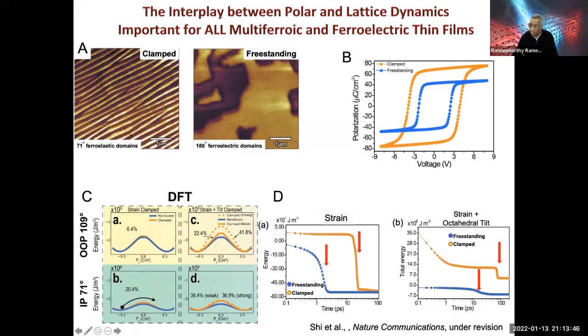Now, we went back to our theory colleagues, both DFT and phase field, and I'll just show you the DFT data. What Jorge again showed was that if you look at BFO, it switches in two steps, 109 degrees out of plane and then an in-plane 71 degrees. But if you look at this picture in C and D, it's telling you that when you have a film that's completely clamped, and BFO has octahedral tilts about the 111 direction, when you clamp it, it takes a lot more energy.